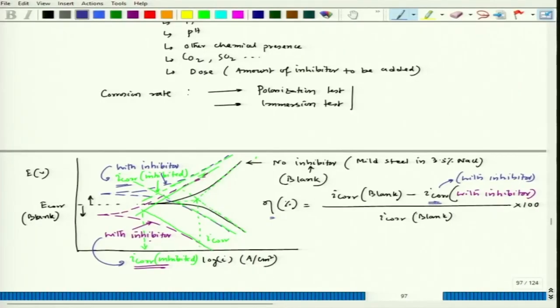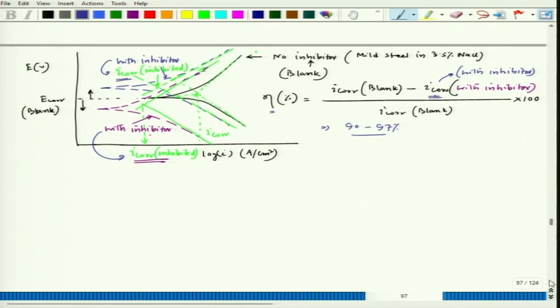You could see that if I corr with inhibition is very low, then of course I could get a very high inhibition efficiency. So even we can get close to 90 to 97% inhibition efficiency. So like one particular small set of data, I don't want to indicate how we got those data. This is experimental data, what we have found at IIT Kanpur. So this is related to green inhibitors. So one such example data set.